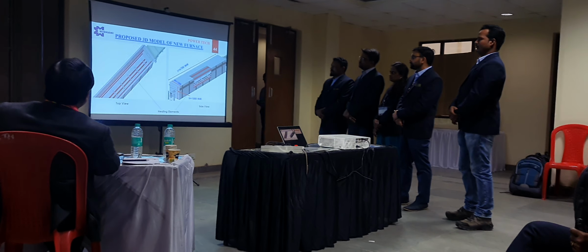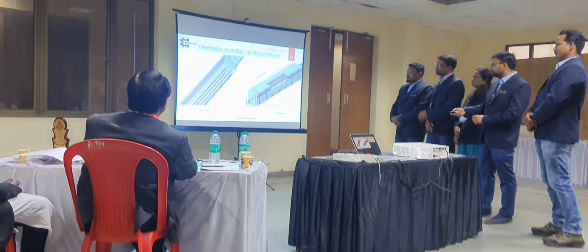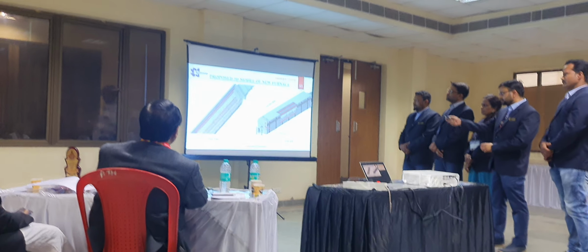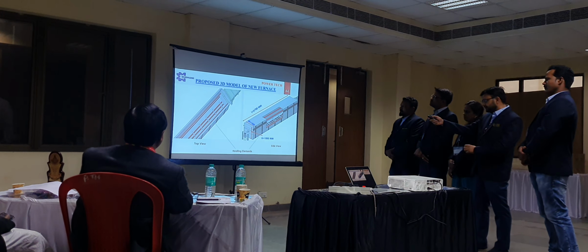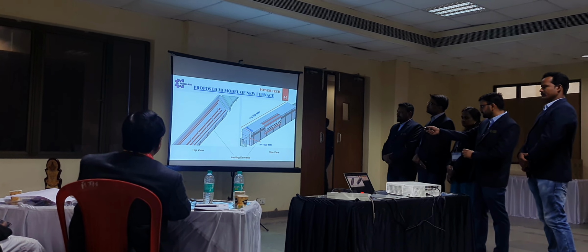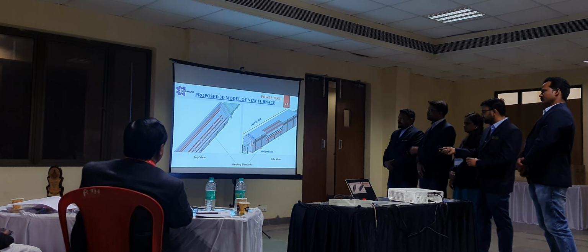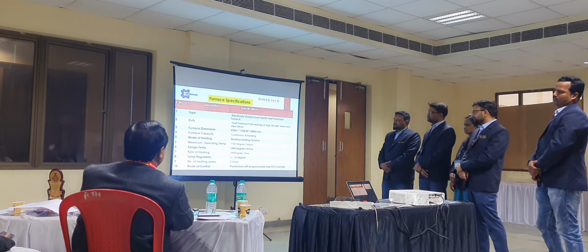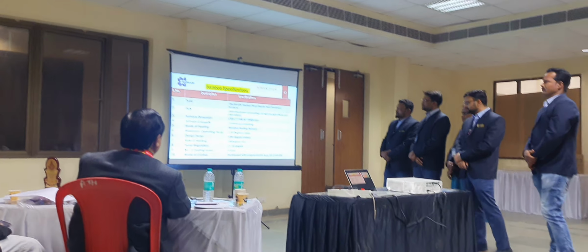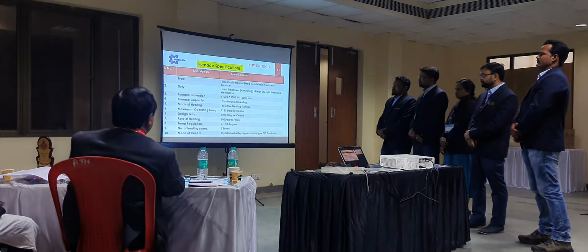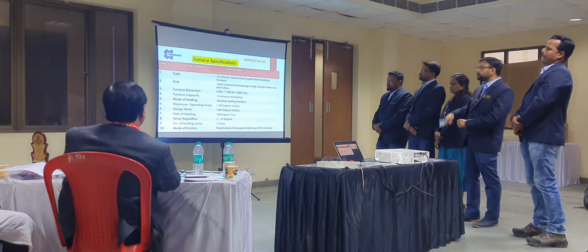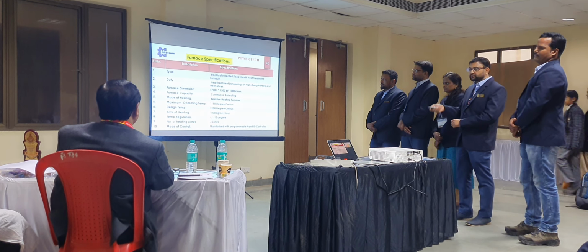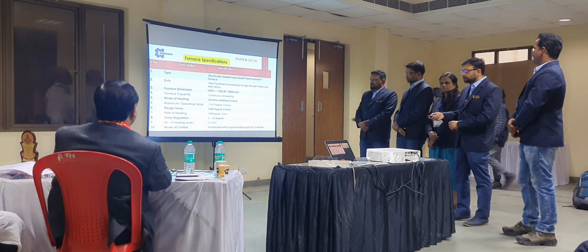This is the proposed design for our new furnace, where we are showing the top view and the side view of the furnace, where the red part is the heating element in the side walls and the bottom parts, and these are the dimension details of the furnace. This is the key specification of the furnace. This is a resistive furnace, and this time we designed the furnace to reach up to 1150 degrees Celsius, as we found in the Gemba verification that this much temperature is required for annealing of high strength wire.